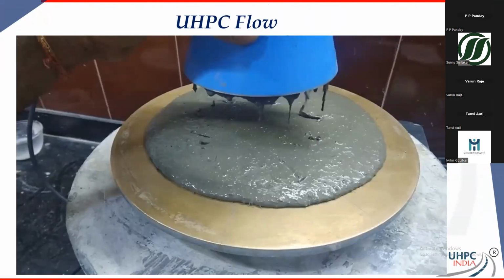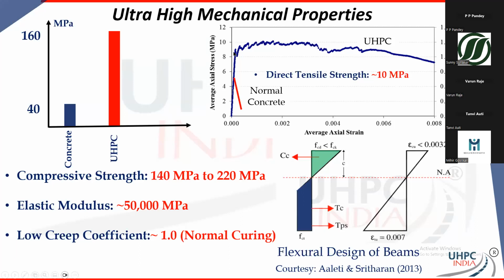Moving ahead, for everybody interested in the technical data over here, right at the top you see how you get strain hardening with UHPC, and all the way to 0.006 strain before it starts strain softening, right? Compare it with normal concrete, you can get up to 5 to 6 MPa, but you have a brittle failure. So the area under the curve is called the toughness, and you are getting over 100 times much tougher material as compared to concrete right over here, right?